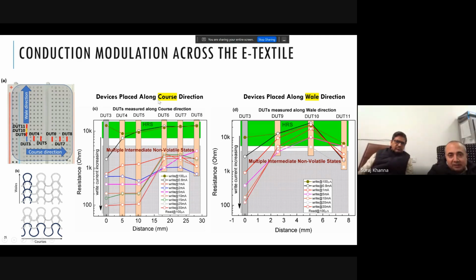So when the device was tested in the course direction, we saw a more uniform spread of heating. What is happening here is we are applying current only across this blue DUT3, and we were trying to understand, if we apply heat just here, how much it can extend in this direction. All these DUT 5, 6, 7, 8 were only measured along this direction.